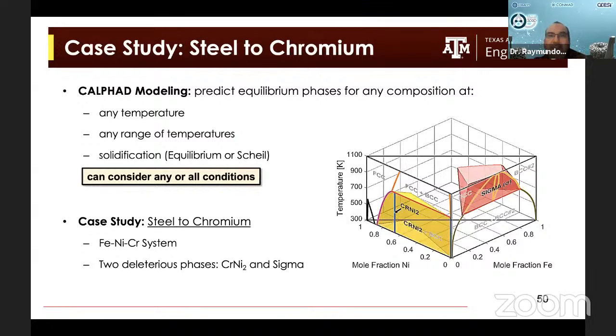We have done many since then. In this case, we actually tried to find a path between steel to chromium. So this is a 316 stainless steel. It's an iron nickel chromium alloy to pure chromium. And we considered that we didn't want to see chromium nickel 2 and sigma phase. We consider that those two phases are deleterious. And the task was to find a path that could actually clear those obstacles at all temperatures and be free of cracks if we were able to build it, right?